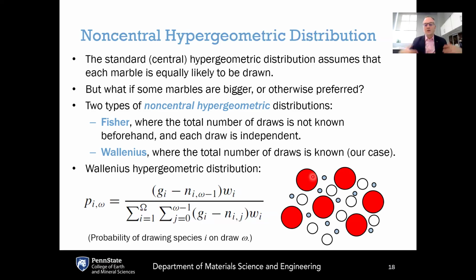So if you've got a greater number of, say, white marbles or blue marbles, then those are more entropically favored compared to the red ones. So in this case here, the red marbles are more energetically preferred because they're larger. Each individual one is more likely to be drawn, but there's a fewer number of them, so they're entropically less favored. So this brings us to what's called a non-central hypergeometric distribution.